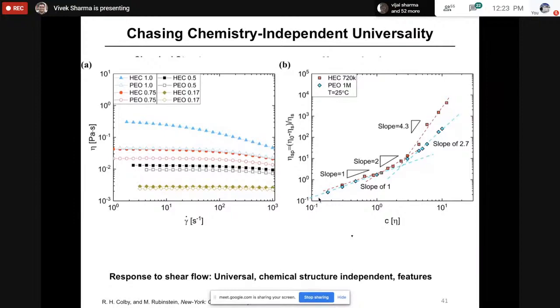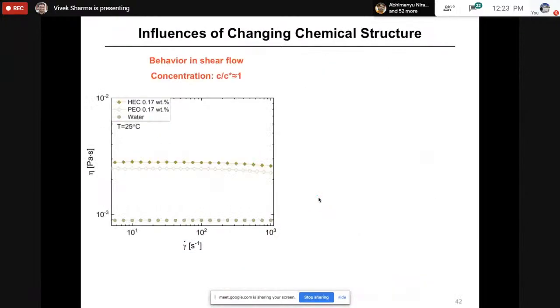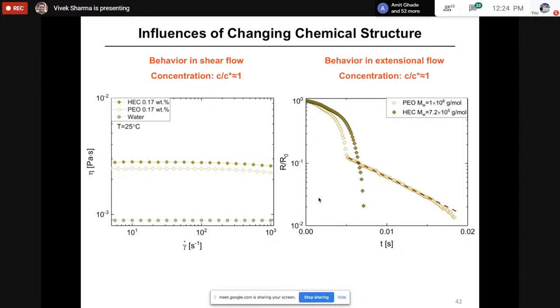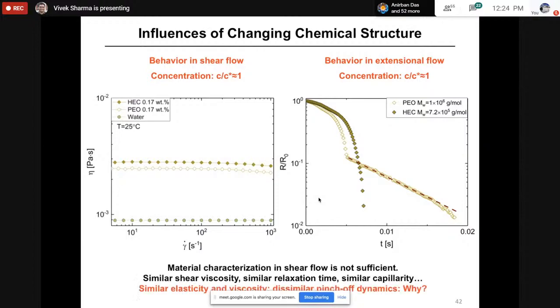So based on this dilute solution, we have similar viscosity, and an estimate of the Zimm relaxation time is also the same. Now we want to figure out what happens if we take this system, and here I'm showing you an example where they have the same actual concentration, same measured shear viscosity, the estimated relaxation time is the same, and they are in water, so their surface tension is the same. However, the pinching dynamics is very, very different. PEO has this delayed pinch off, HEC does not. So you can't explain these differences based on just shear viscosity or relaxation time or surface tension effects.